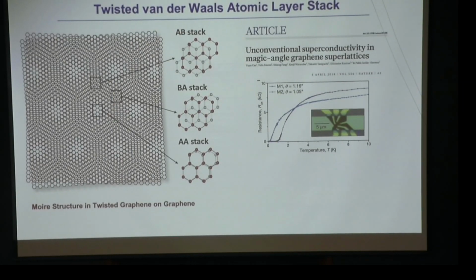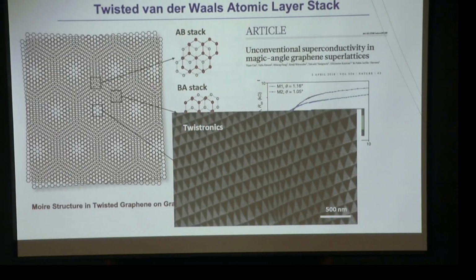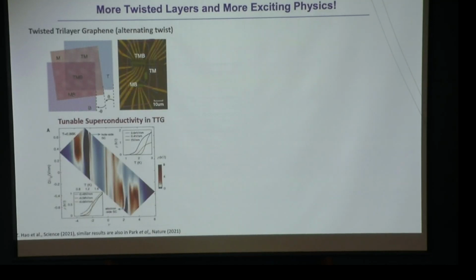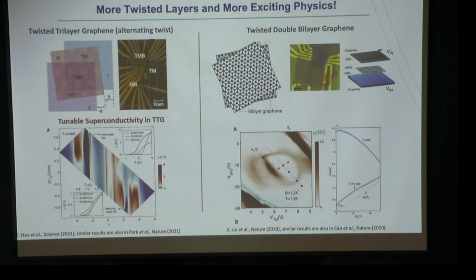Part of the reason is that when you form this layer, you get all these strains and you have the reconstructions. How come a simple theory based on the tight-binding model or the continuum theory, without consideration of the relaxation, can be right for this surprising reason? Well, there were a few people who really pursued this with full heart and saw those exciting things. Of course, once this type of seminal discovery was made, many people repeated those experiments and quickly expanded them. For example, not only single layer, if you go to multiple layers, 3 layers, 4 layers, now 5 or 6 layers, it can be not only single layer graphene but bilayer graphene, you get these superconductivities and magnetism.